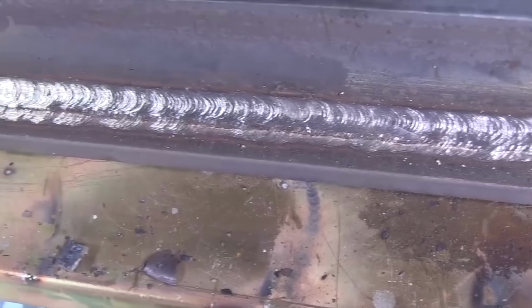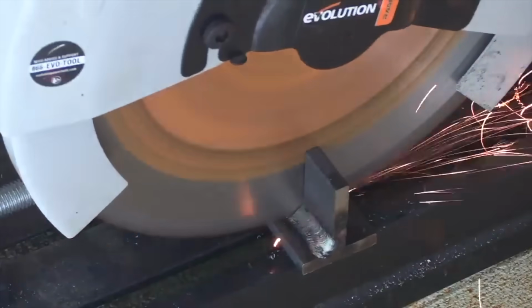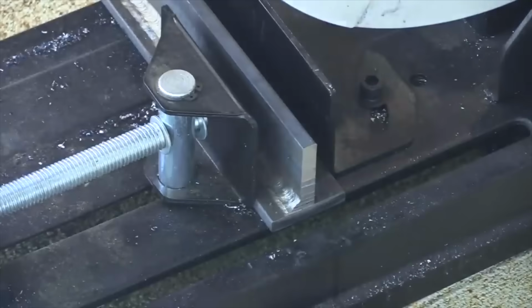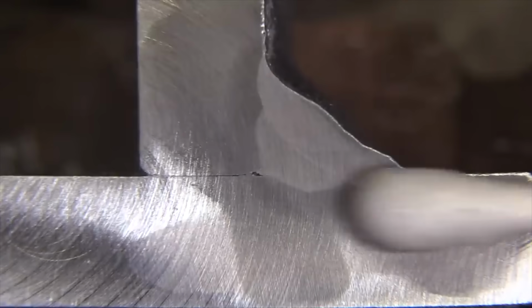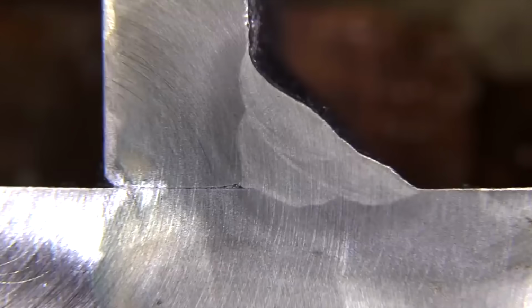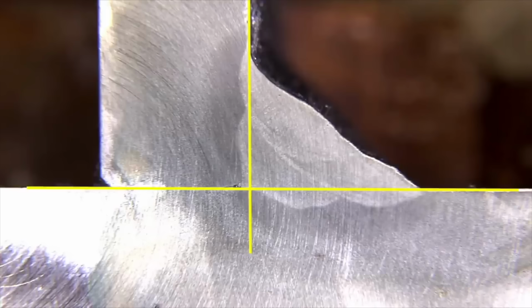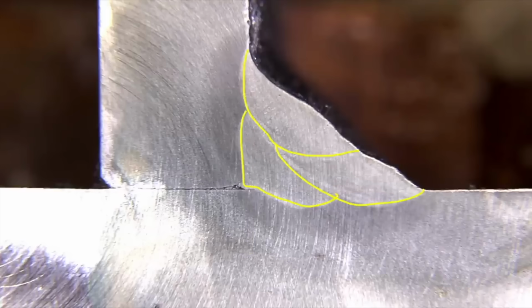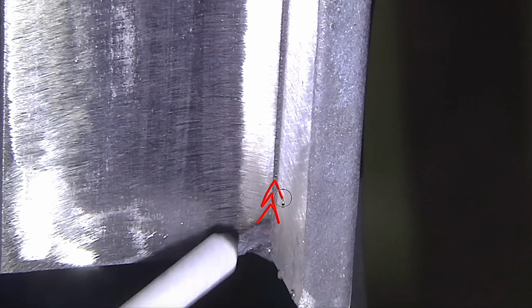For 7018, I had just found that running it kind of on the hot side for flat and horizontal will help a lot. And don't be scared of the heat on overhead. You see me doing a cut, polish, and etch here too, and you can really tell each layer of that weld. You can see the root pass and the subsequent two passes, and that's very informational. That's very instructive to do a cut and etch right after you weld something. You can really tell what happened.